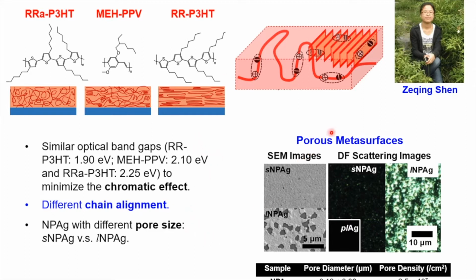We studied the impact of porous silver metasurfaces with different pore sizes and pore densities on the fluorescence from these polymers. These were made using a de-wetting process, and they were over a large area, typically a few centimeters squared, because ultimately we wanted to integrate these into devices. You can see the pore diameter for the small nanopore silver was 0.12 microns with a pore density of 2.5 by 10 to the 7. And for the larger nanopore silver, it was 1.3 microns with a slightly lower pore density.